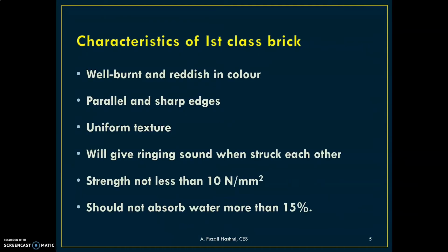The characteristics of the first class bricks are: it should be well burnt and reddish in color. They have parallel and sharp edges. They have uniform texture, and they give a ringing sound when struck with each other. The water absorption in the first class brick should not be more than 15% when it is immersed in water for a period of 24 hours.